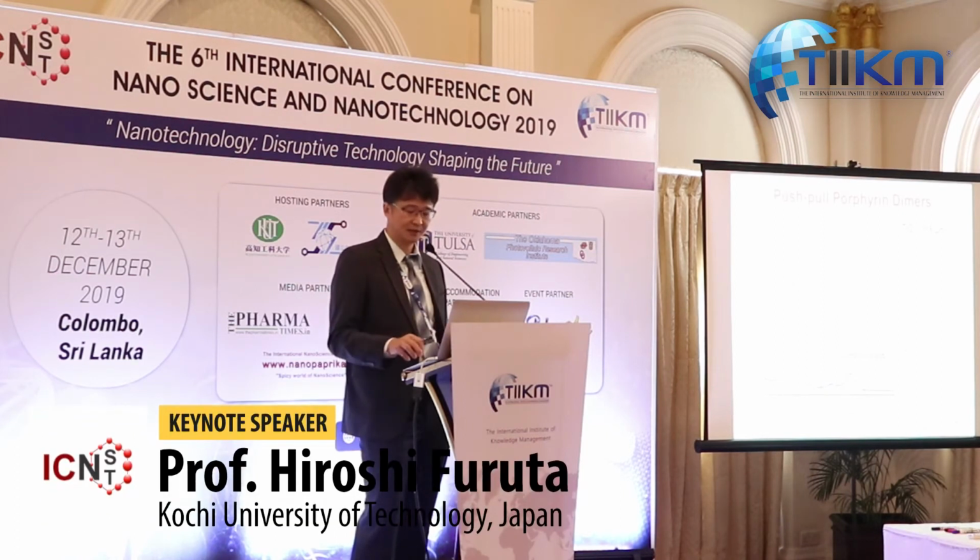We also made push-pull porphyrin dimers, YDD4 and YDD5, with a diphenylamine attached to the meso position. Dimer YDD5 shows slightly better efficiency than YD2 for thin film samples because YDD5 has better light harvesting property. Under optimized conditions carried out in Professor Grätzel's group, YDD5 achieves an efficiency of 9.6%.